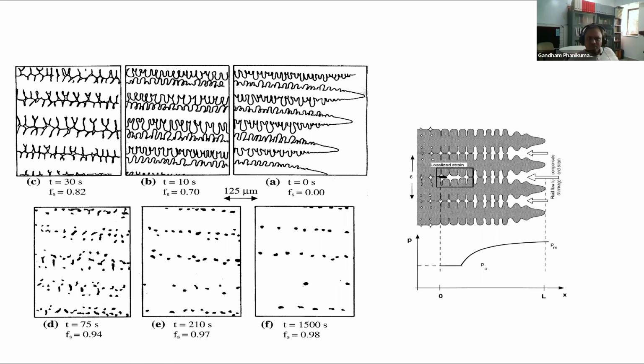Now, how does that relate to printing? It's very simple. If you have a cracking problem in an alloy where the microstructure happens to be dendritic, then try going slightly faster with respect to the laser scanning speed so that your microstructure is slightly finer, and maybe you will have a lesser cracking problem. Okay, so that is a direction, a thumb rule we can try to use.